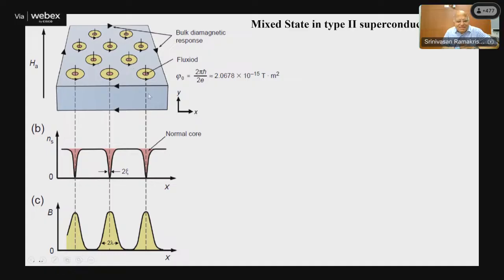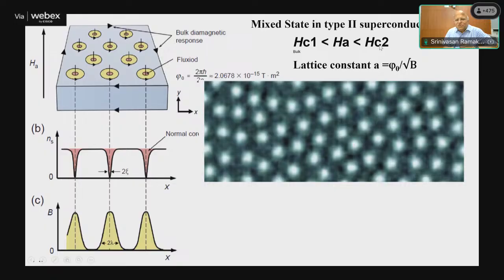At the center you have a normal core where psi is 0, and the field completely penetrates here, and then the field gets expelled as you move away from there. So you can see this is the 2 xi and this is the 2 lambda. This is actually observed. This happens, as I told you, below the upper critical field Hc2 and above Hc1. And they seem to form a triangular lattice.